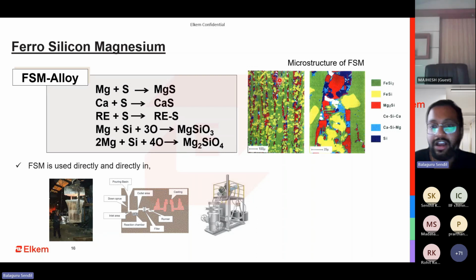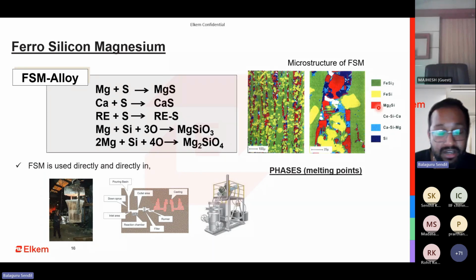If you look at the microstructure of ferrosilicon magnesium, this is how it looks. This is an image from SEM. We have done EBSD, and then we have seen what the different phases are. In the previous slide, we saw only magnesium, which starts melting at about 600 degrees Celsius and boiling at about 1100 degrees Celsius. But in ferrosilicon magnesium, you have iron, silicon, magnesium, sometimes cerium, sometimes lanthanum, sometimes calcium also. It's highly customizable as per the foundry's need.